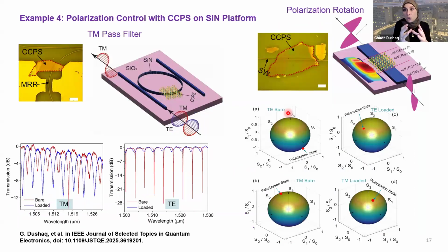The other thing is that they can also work as a polarization element, where we demonstrated this in a ring resonator and also in a straight waveguide. So you could see that on the ring resonator, because of the polarization-dependent mode geometrical aspect, you can have a transverse magnetic all-pass filter, preventing all the transverse electric and attenuating it. So it's a polarization dependency between the two perpendicular polarizations inside the chip, because we have a quasi-TE and a quasi-TM.